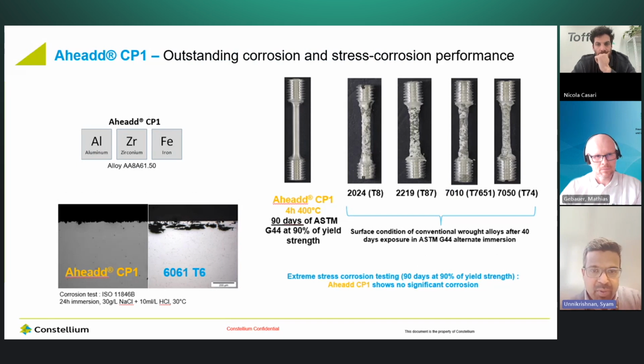Another important property of Aheadd CP1 is the outstanding corrosion and stress corrosion performance. When a design engineer designs a component, he would like to make sure that the components survive extreme conditions, particularly heat exchangers or heat sinks when those are exposed to extreme conditions. So when we compare Aheadd CP1 with 6061 T6, one of the standard alloys in the market, you can see on the left-hand side, bottom area, CP1 is an outstanding performer in terms of corrosion. There is no visible attack for the 24 hours immersion test, whereas on 6061, you can see from the surface there is an attack happening.